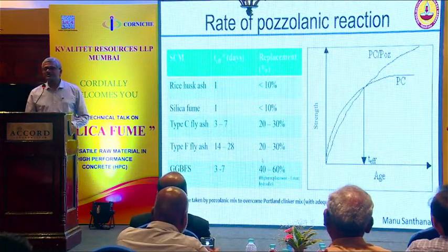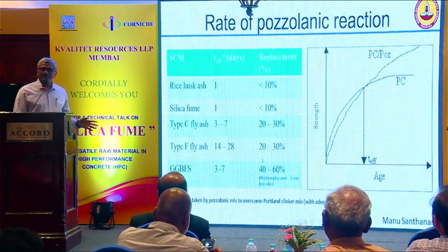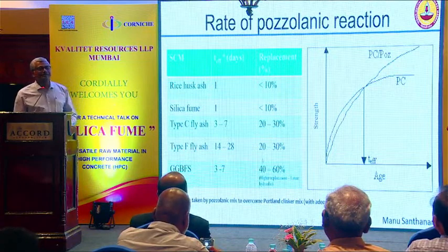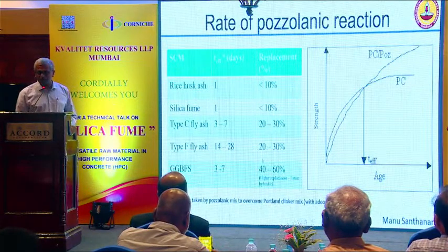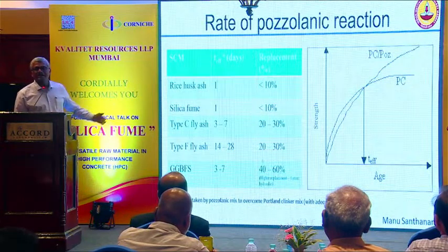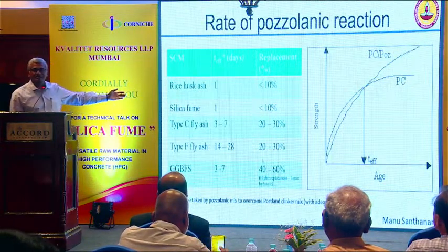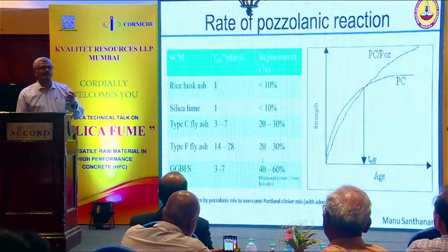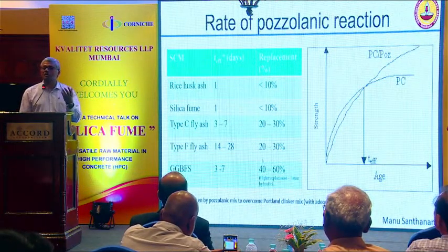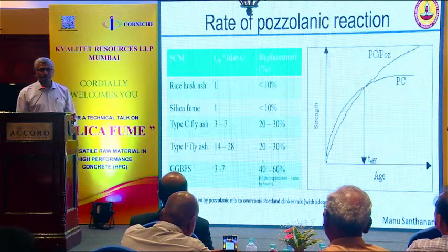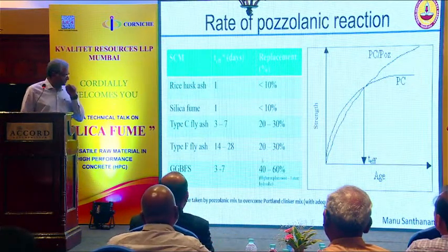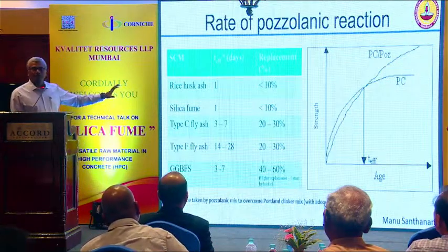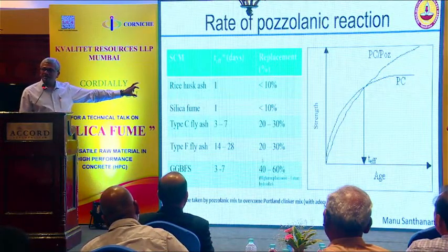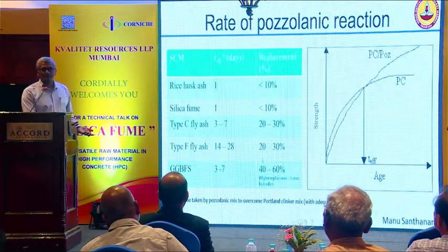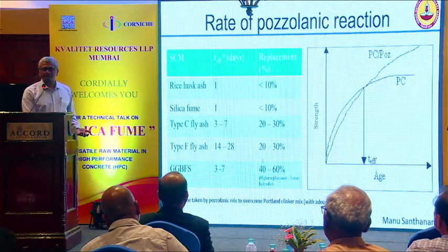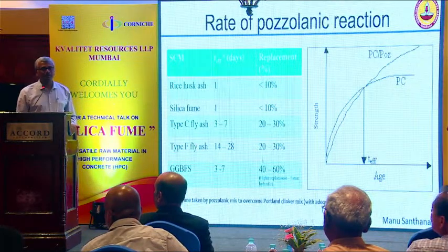One thing we need to understand is these different mineral admixtures will have different rates at which they are providing the necessary property, right? So if we look at highly reactive materials like rice husk ash, when you burn rice husk in controlled conditions, it gives you a very high purity silica also, right? And silica fume, again, very high purity silica. So both of these, at one day itself, they'll be matching the performance you expect with cement. That means there is no slowdown in the rate of hydration.